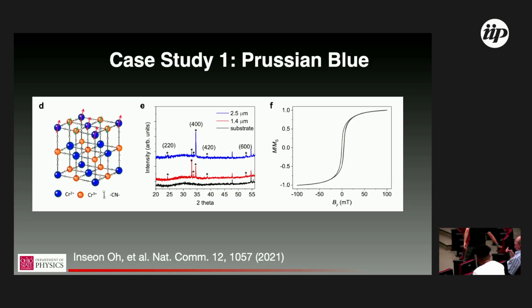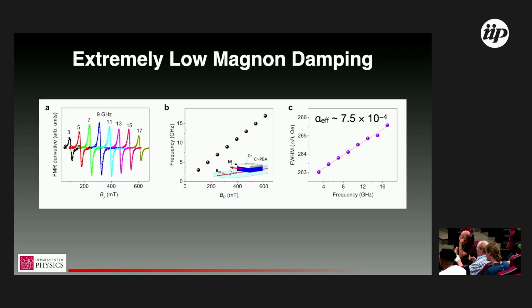I would simply like to comment on something which may also be a link to my talk. If you could go back to the damping. It is remarkable that you have 7.5 times 10 to the minus 4, but it's also remarkable that the line width changes by 3 Oersted, but it is already at 260. So that means this is extremely inhomogeneous material.